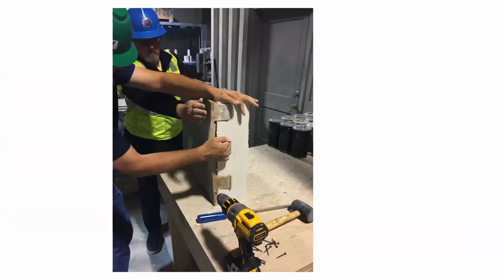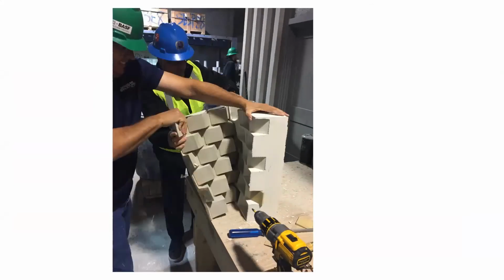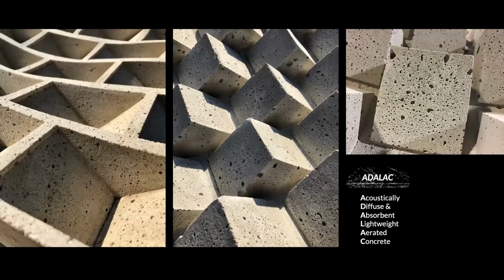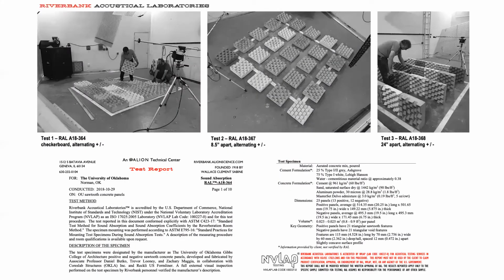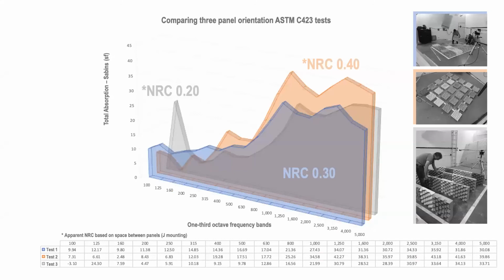Here's an example of the form being stripped from the panel. The concrete experimentation yielded prototype concepts with a working name ADALAC, acoustically diffuse and absorbent lightweight aerated concrete. Riverbank Acoustical Laboratories in Geneva, Illinois performed 3 reverberant chamber tests, which emulated potential installation methods as suspended panels, banners, and/or wall or ceiling surfaces. The 3 tests resulted in NRC and equivalent or apparent values due to the space between some of the panels of 0.3, 0.4, and 0.2.